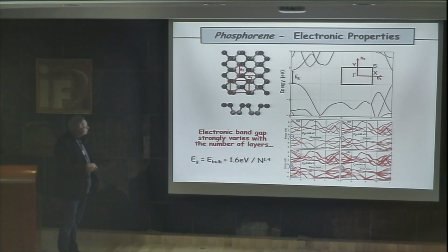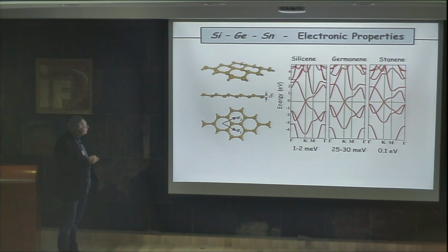So you have this puckered material for phosphorene, and here you have a kind of buckling of the plane. This is because the silicon-silicon bond is much longer compared to the carbon-carbon bond. And in order to maximize the overlapping between pi electrons, in fact, you need to have this buckling in the plane. And the buckling is even more important for germanene and for stanene. But you see, you conserve this linear dispersion here close to the K point, which is similar to what you observed in graphene. But in this case, again, if you switch on the spin-orbit coupling, you will observe that you have the presence of a band gap in the system, and you can really control that.